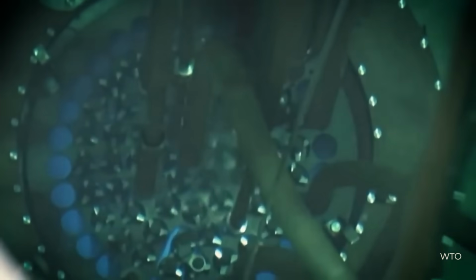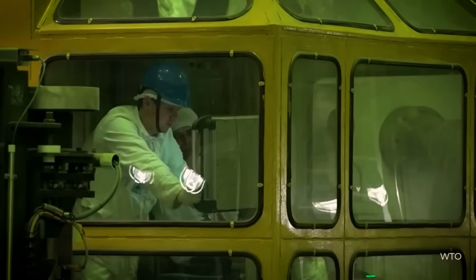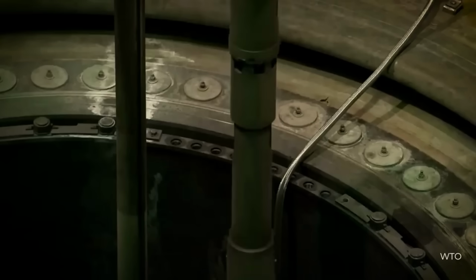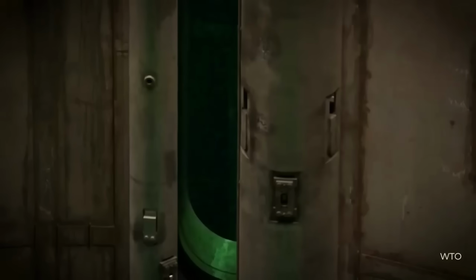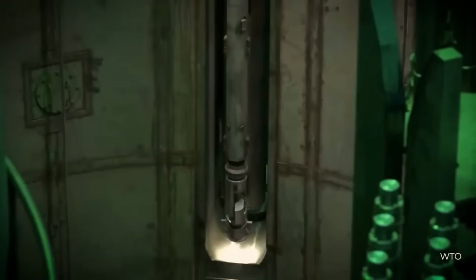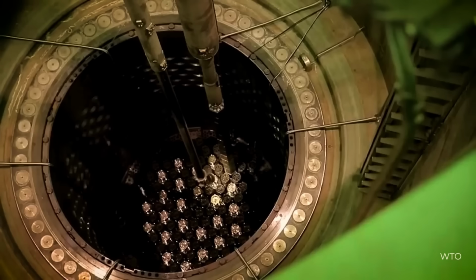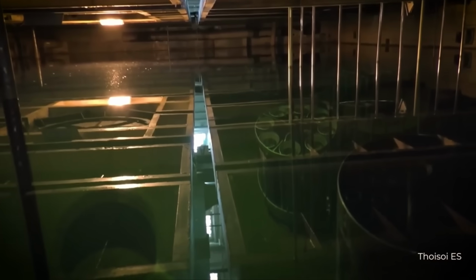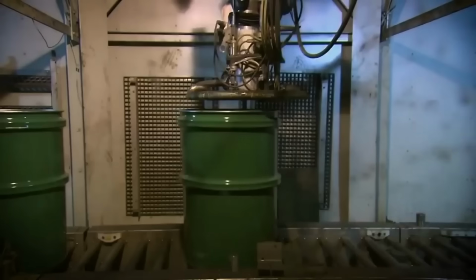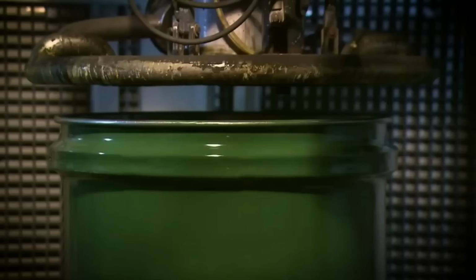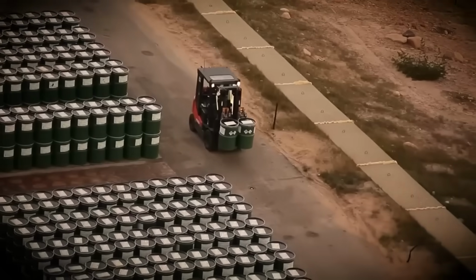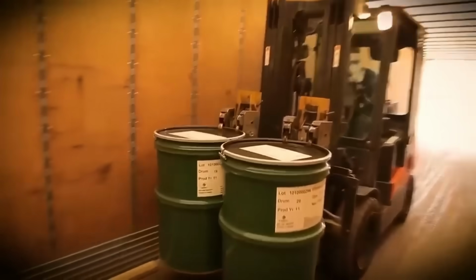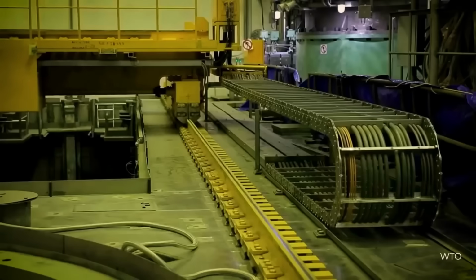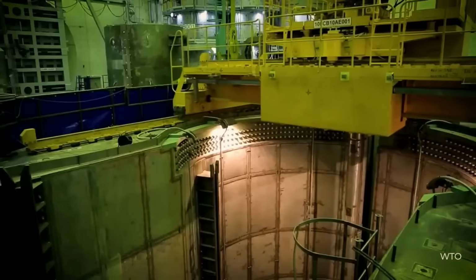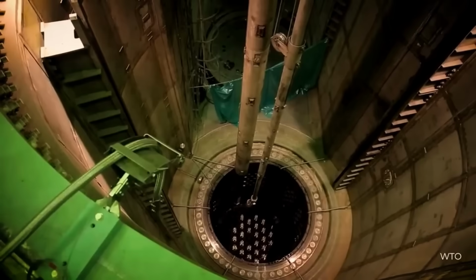Operating at 800 degrees Celsius, the kiln evaporates the acid in a controlled process lasting about 6 hours, leaving a fine neptunium oxide powder with a sandy texture and a slight metallic sheen, similar to the sand on a volcanic beach. This powder is mixed with aluminum powder in a precise ratio of 80% neptunium oxide to 20% aluminum, which acts as a binder to facilitate pressing. The mixture is transferred to an automatic pellet press, a high-tech machine that works with the precision of a chef